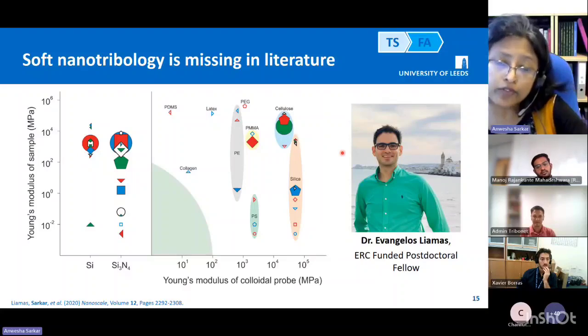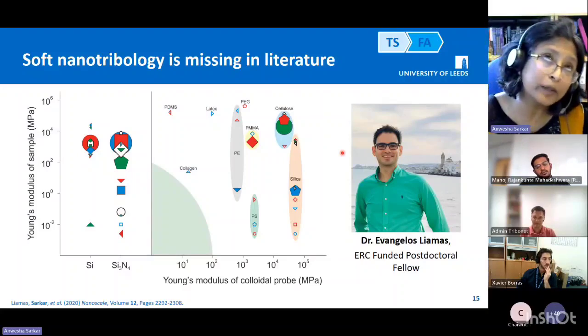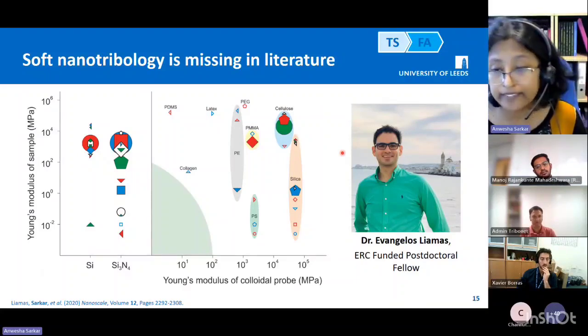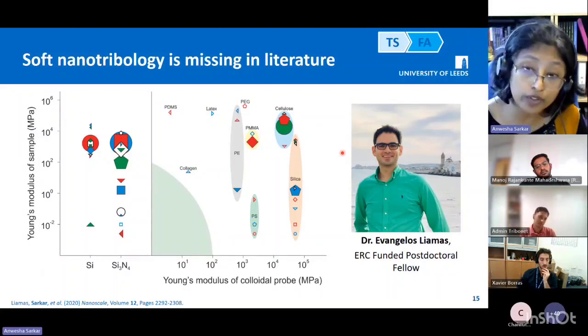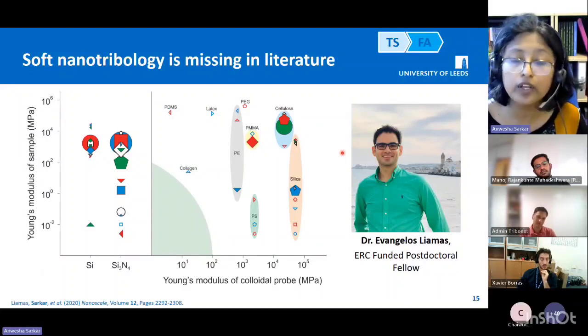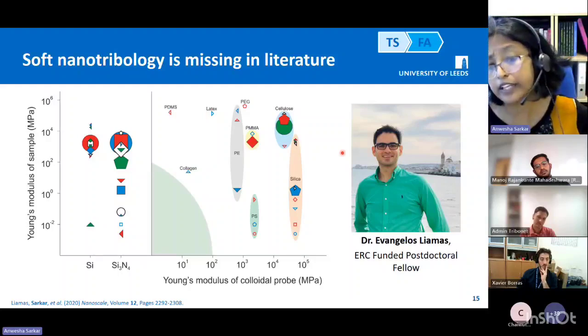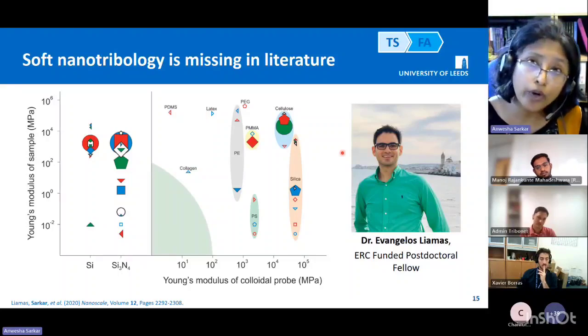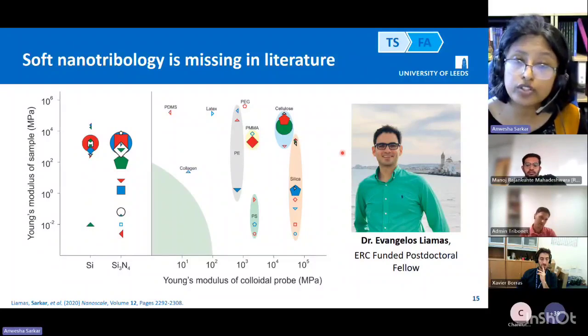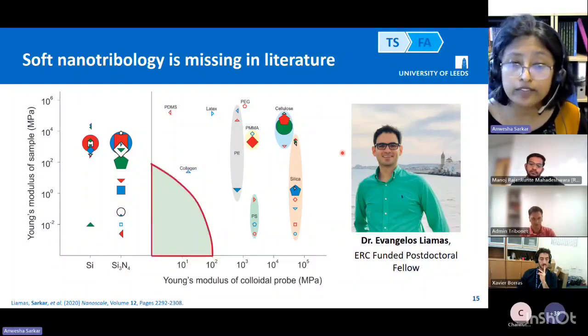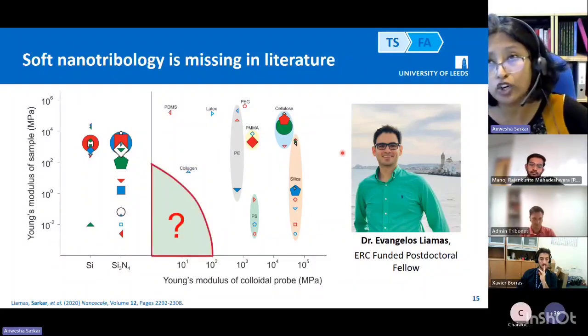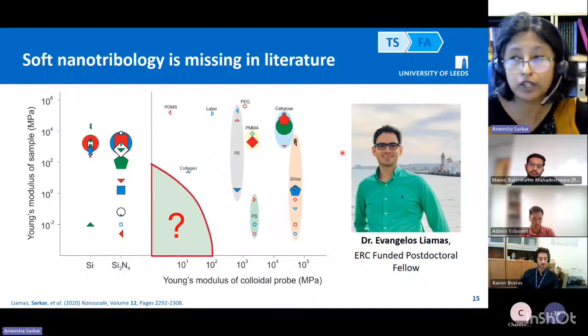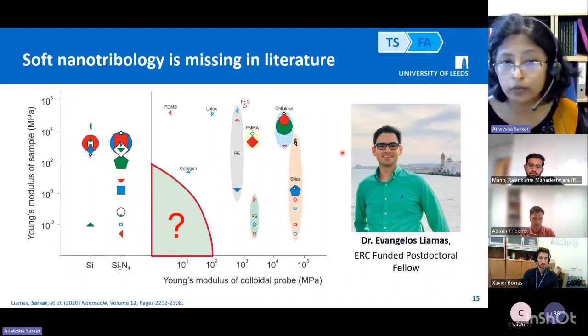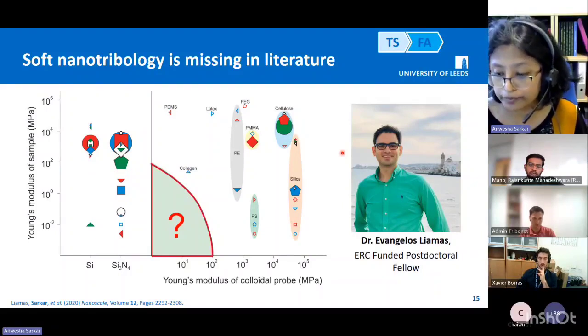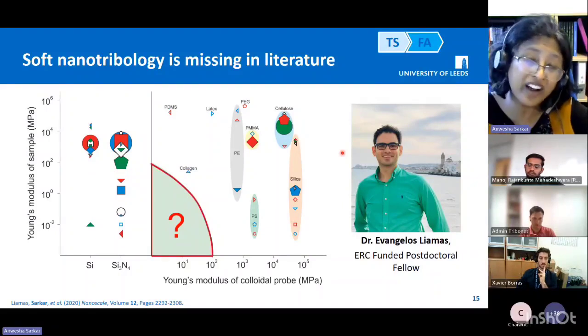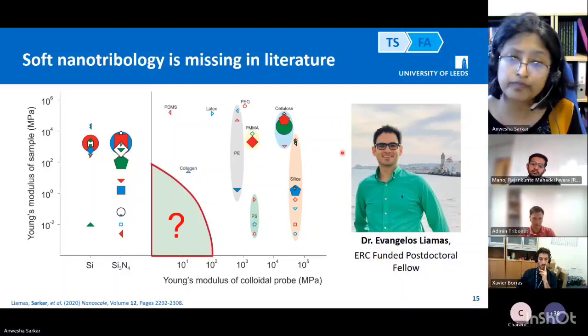So at the nanoscale, again, we did not do a real tongue, but as I mentioned, we were doing a papillae. And this work was done by Evangelos, who was also our ERC-funded postdoctoral fellow. And we did a massive screening of the literature to identify what work has been done on soft probes. And what we identified is that this is the area where we are talking about around 100 to 150 megapascal, where there's very little work in literature on colloidal probes. So they're all very, very hard colloidal probes.